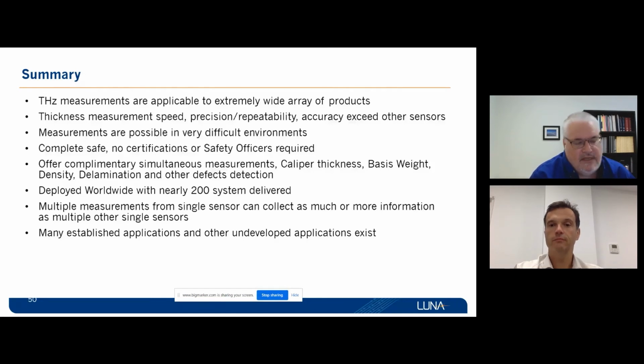But that probe is not only able to measure once at a time, it's layer at a time. It can be like ultrasound. If you try to imagine that very first graph, if you have multiple different kinds of materials or mixtures of materials, you can measure the thickness of each one separately with one probe, so one time. So essentially, you can measure not only the top coat thickness, but the thickness of everything underneath it until you hit the copper mesh. But it depends on the size of the copper mesh. If the copper mesh is big enough, the beam's going to go through the holes too.